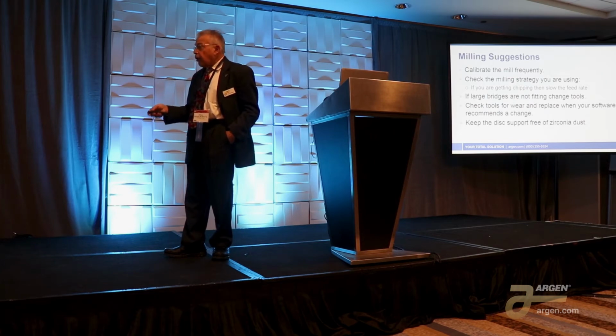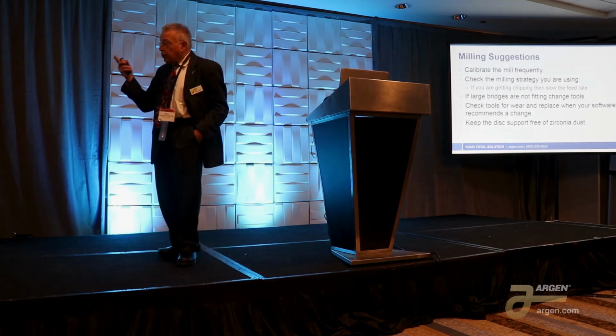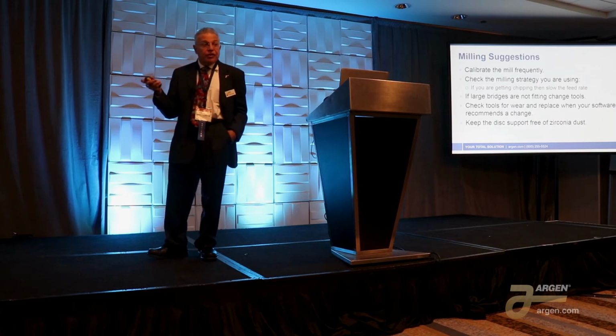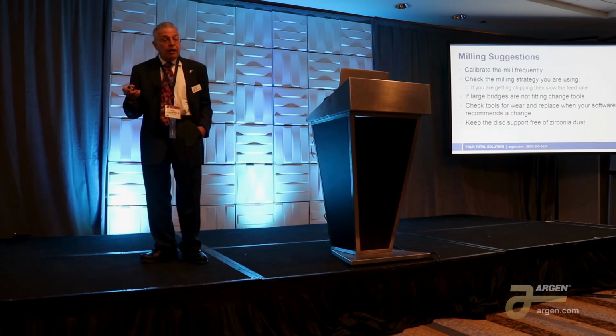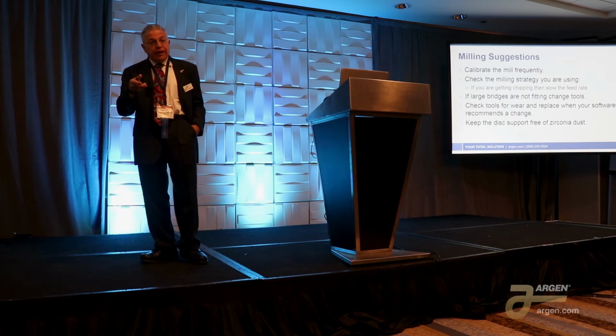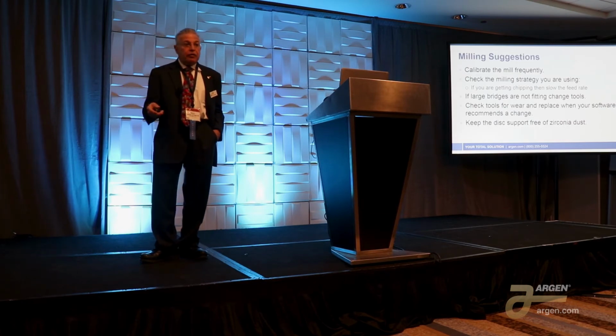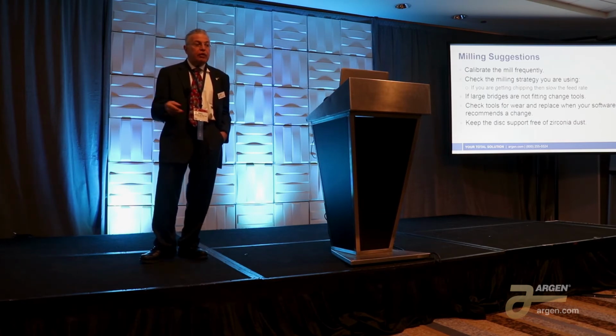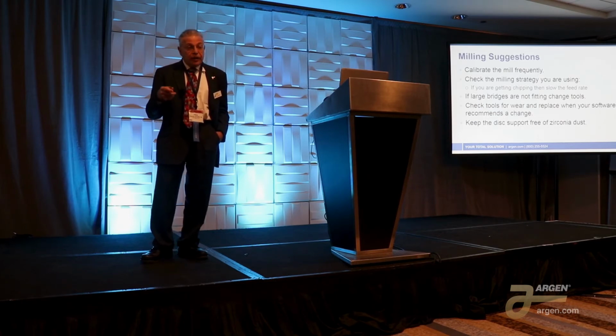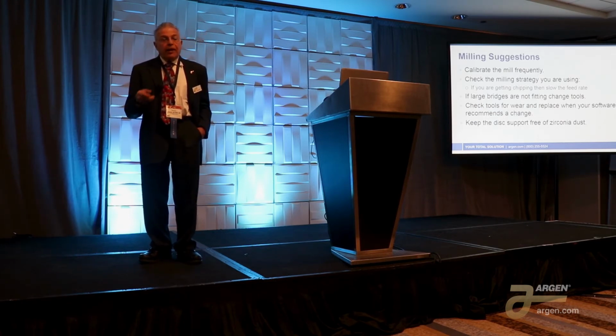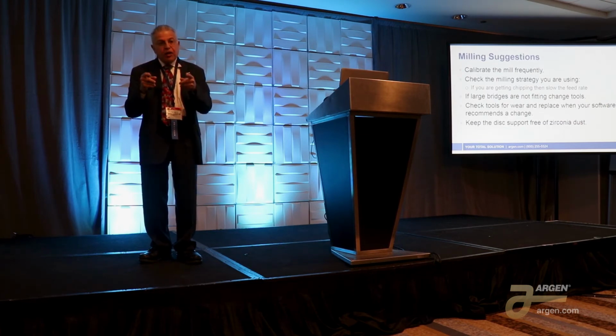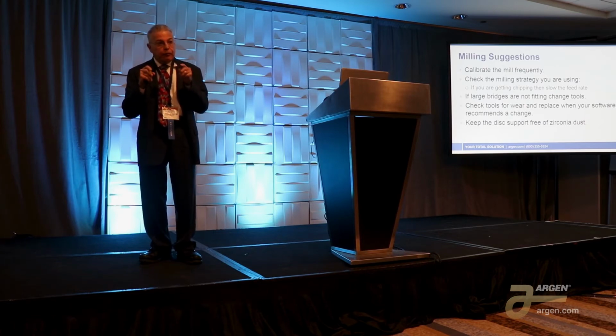Okay? If large bridges are not fitting, as I said, one reason is that the calibration is off. The other reason is that your tools are dull. Zirconia, I said from the beginning, can only be damaged by diamond, which means zirconia is damaging everything else. Zirconia is much harder than the end mill you're using, even if you use a diamond-coated end mill. So it's going to wear that end mill down. And when it wears it down too much on a bridge work where you get a significant amount of span, you're actually going to be off the size. So it's not going to fit properly.